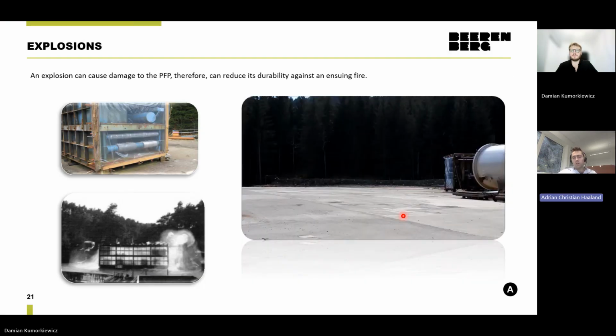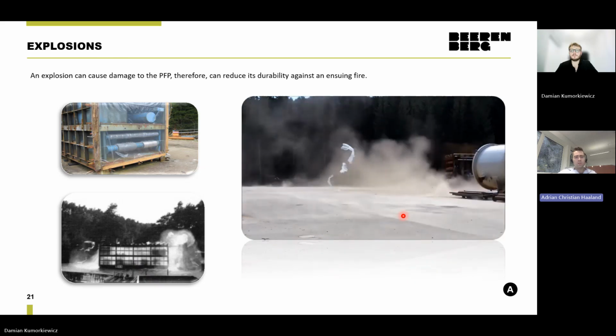Then we also do explosion testing. This is from an older test where the test specimens are located in the front of an explosion container. The container vessel is filled with an explosive mixture of air and propane in this case, and when it's detonated in the back end, the pressure wave builds up, and typically the more congested you have these process areas, the higher the pressure will build up.